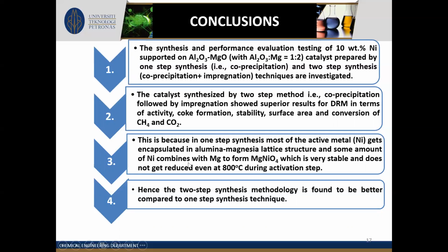This is because in the one-step method, most of the active metal sites get encapsulated in the alumina magnesia lattice structure, and some amount of nickel combines with magnesium to form MgNiO4, which is very stable and does not get reduced even at 800 degrees Celsius during activation of the catalyst. Finally, we can see that the two-step synthesis methodology is better than the one-step synthesis technique.